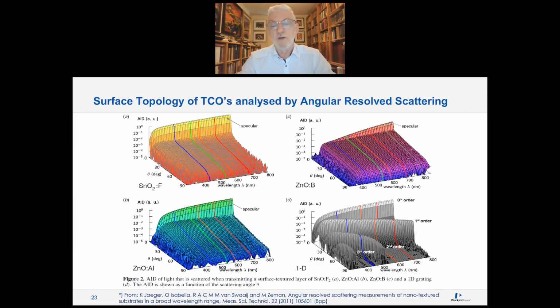And these are typical measurements they made. They measured from 400 to 800 nanometers, mostly at different angles of incidence. This took about 12 hours to record all the measurements with a Lambda 1050 and the ARTA, fully automated. And they used that to optimize and to get the information on the topology.